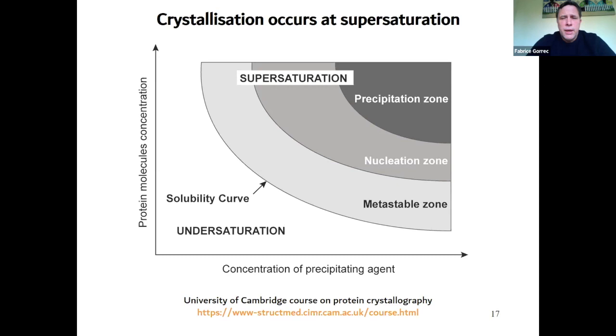And here, it's a two-dimensional view of this, and basically the protein crystallizes in what's called the supersaturation zone. And here through the curve, you see that when the saturation increases, the protein crystallization increases as well. This is done by increasing the concentration of the precipitant agent. You go through a metastable zone, a nucleation zone, so we're getting really saturated at this stage. And then if the crystal nucleates, it will be in this zone. And if you go a bit too far, obviously, you have a precipitation.